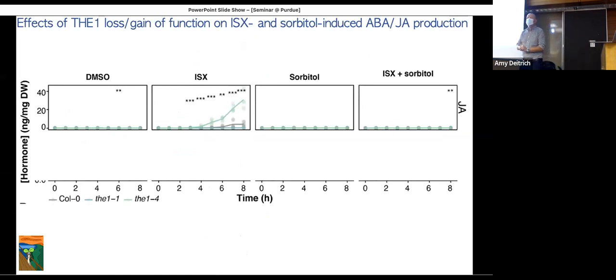What you see quite nicely is that you have your wild type control, called 0, and the two alleles for THE1, loss and gain of function. DMSO doesn't really have any effect. Sorbitol also doesn't induce jasmonic acid. When you look at isoxaben, you see induction in the wild type, less induction in the THE1-1 loss of function, and more induction in the THE1-4. And interestingly, in the double-treated seedlings, isoxaben and sorbitol, nothing, blank. So that is what you would expect to see if THE1 regulates jasmonic acid.